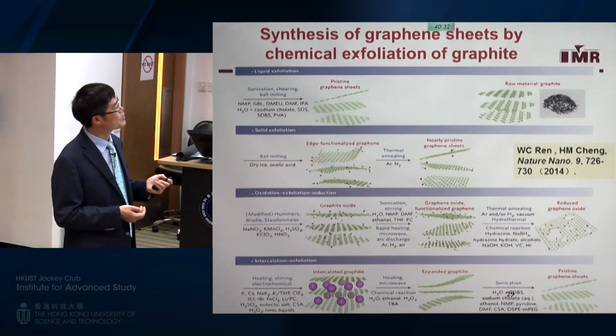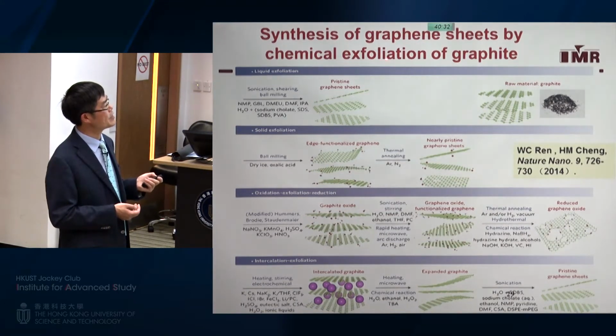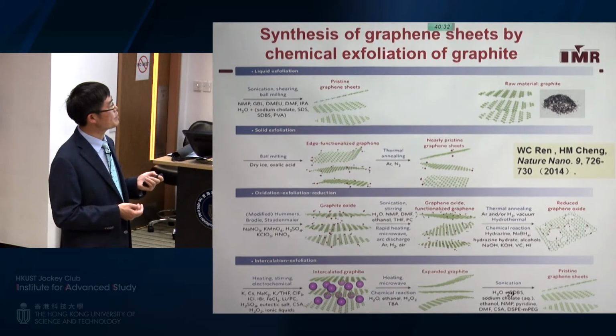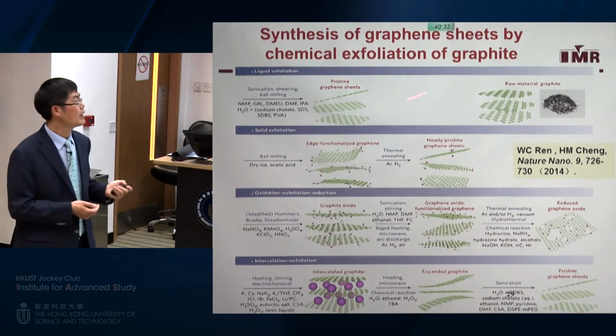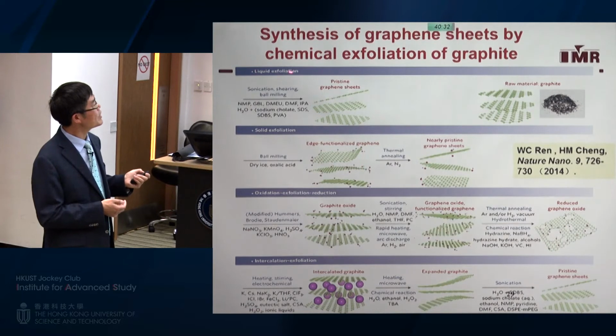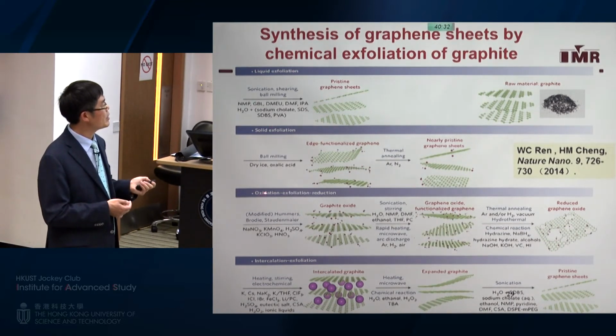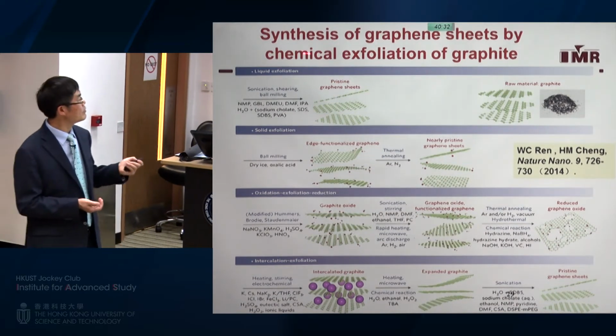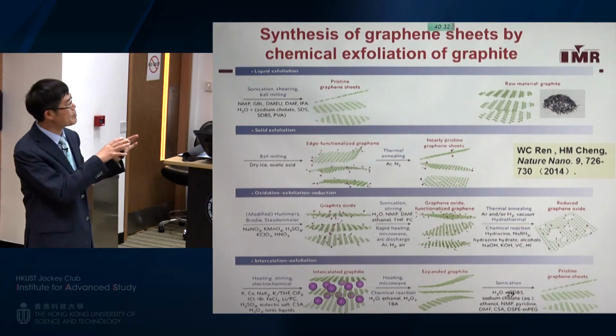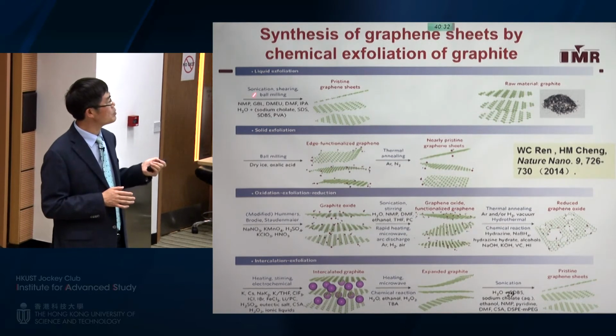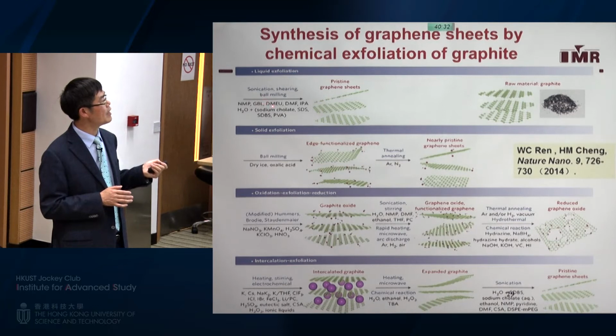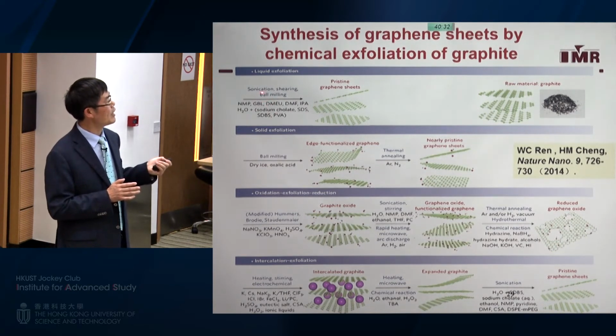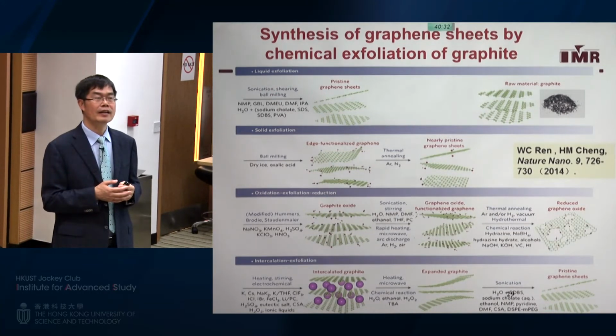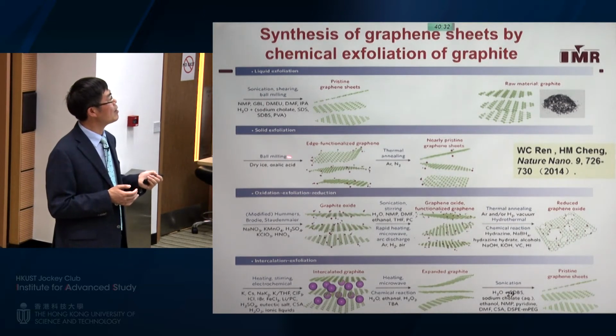So basically, we use graphene from chemical exfoliation methods. Chemical exfoliation methods can be classified into these four types: liquid exfoliation, solid exfoliation, oxidation exfoliation reduction, and intercalation exfoliation. For all the methods, basically we use natural graphite. But for those two, we add some surface agent to aid the exfoliation during the sonication or ball milling.